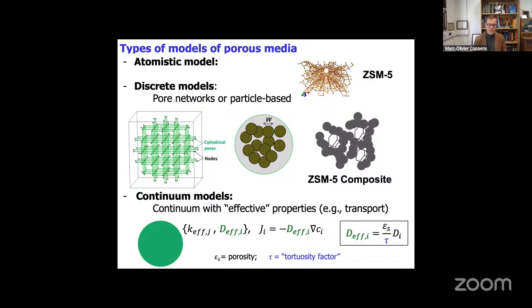And then there is another level, which is continuum models, where you homogenize this whole space, even though in reality it is heterogeneous. And then you have effective properties. For example, relating to our problem of diffusion and reaction, you would have effective rate constants, effective diffusivities. And these effective diffusivities could be part of models like Fick's law as a phenomenological law, relating the fluxes with concentration gradients. And of course, you could get more sophisticated with chemical potential gradients or include Stefan-Maxwell equations and such. But in a way, you are still creating an effective model of this whole heterogeneous space, including solid and fluid, pore space and the solid phase.